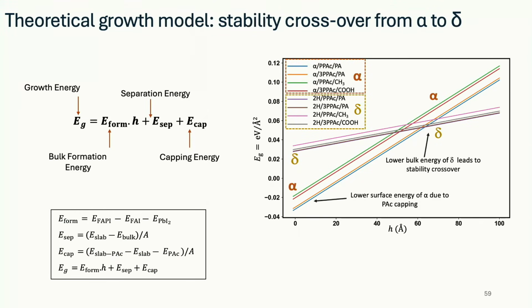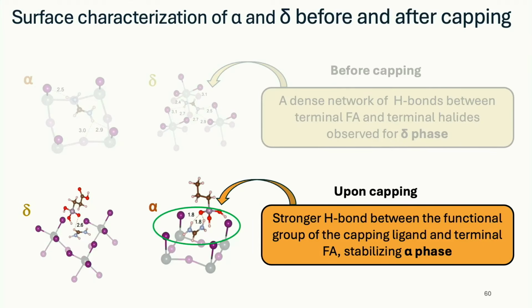And so that leads to this kind of a graph, that if you have the molecules, the alpha phase can be more stable. But if you go thick enough, actually the bulk of the delta phase is favored, but it's too late. Once you've nucleated the good phase, it'll keep on growing even when you go past this crossover point. And so it's really getting it started in the right way with the phosphonates saying, don't worry about your dangling bonds, we got you. And so this is another aspect of materials design based on understanding the physical principles.